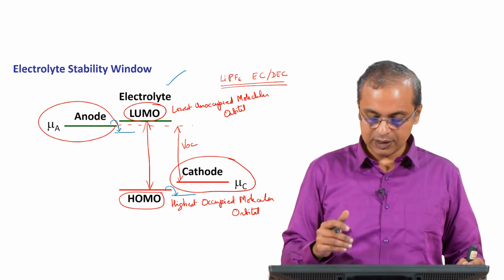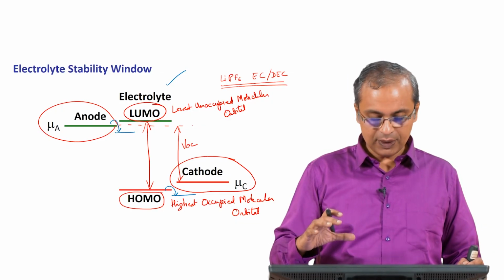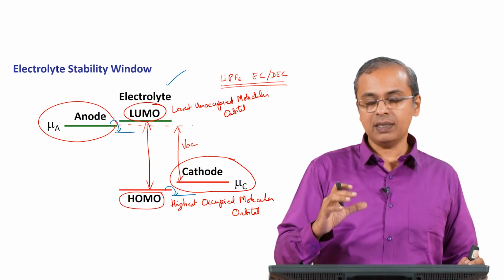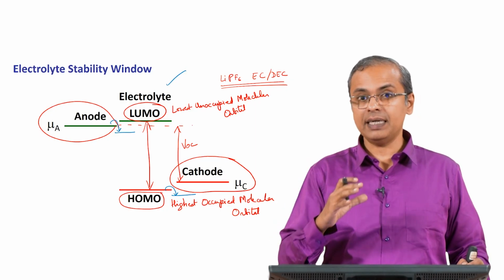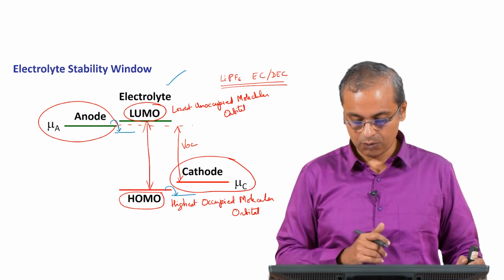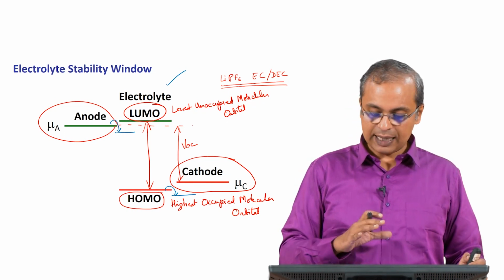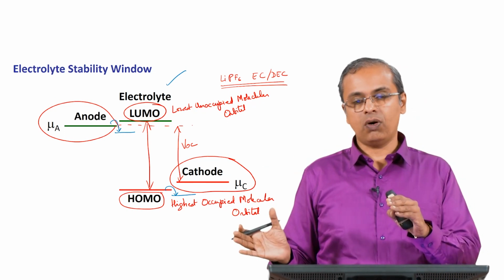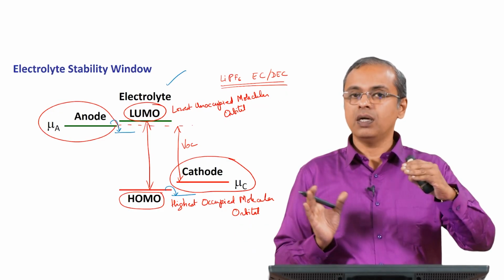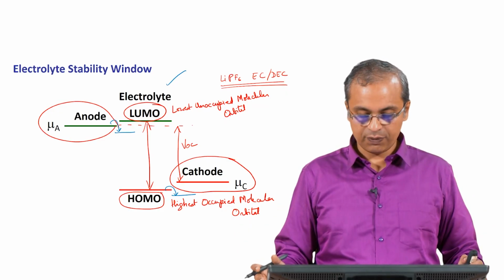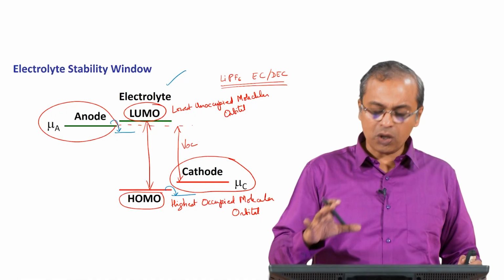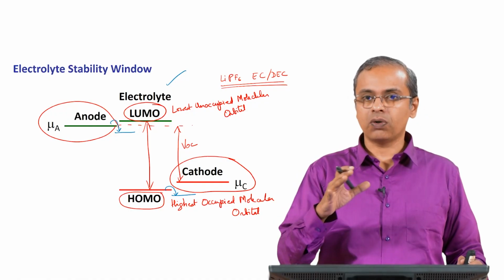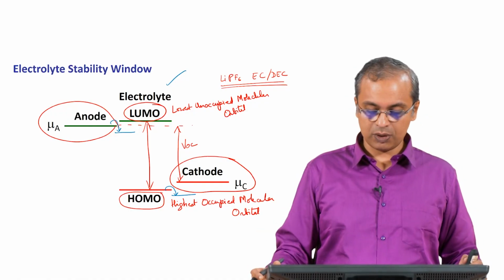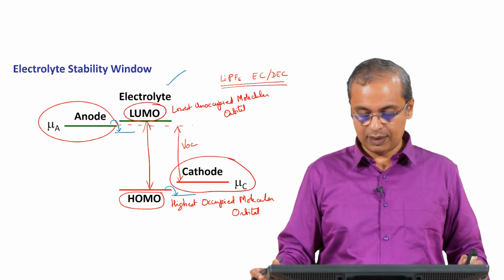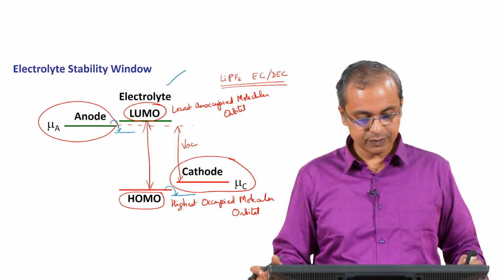So, we basically want a situation where this window between the anode and cathode stays within the window of the HOMO and LUMO of the electrolyte, it is not outside of this window of the HOMO and LUMO of the electrolyte. Okay. So, that is the way in which we match the operating potentials of the anode cathode with the operating voltage window of the electrolyte, and this is true not only for the lithium ion system, it is true for all the electrolyte electrode combinations that you may see in any other battery system.